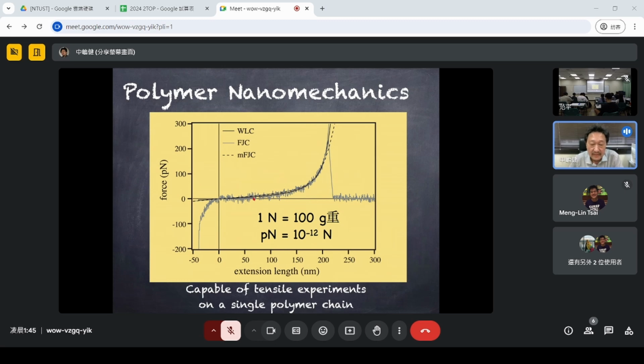Originally, its size is like 5 nanometers or so, because it is in a shrunken form, but by stretching it you can extend it to the maximum, and the total length of the single polymer chain is like 200 nanometers. So 0.2 micrometer, very small. And the force level is also very, very small. It's piconewton level, 10 to the minus 12. So you may not be able to imagine how small that is. But this is for the single polymer chain.